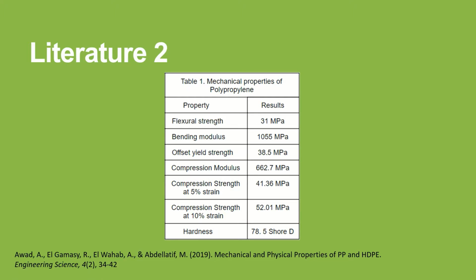Awad et al. in 2019 investigated the mechanical properties of a compression-molded polypropylene through three-point bending test, compression, and hardness. The mechanical testing performed are summarized under Table 1. Results show that polypropylene has good mechanical properties, and it could be attributed to the attachment of methyl on its polymer chain.